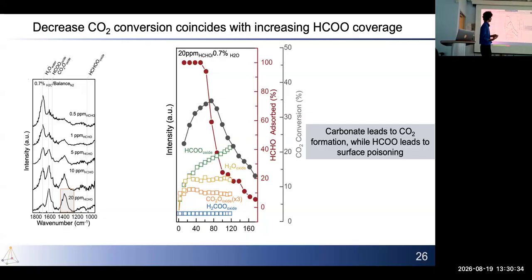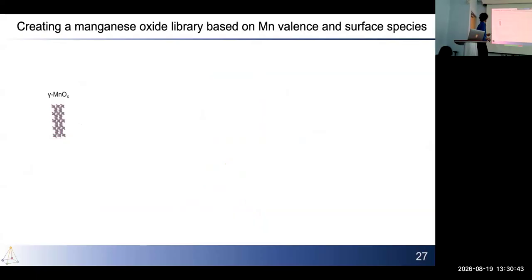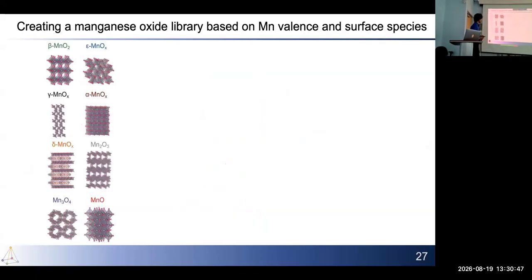We had a reaction mechanism based on spectroscopy, but could we extend this hypothesis to other manganese oxides? The manganese oxide I spoke about so far was the gamma manganese oxide. So we created a whole library of manganese oxides, looking at about 8 different ones to see if the hypotheses and trends we saw with one particular manganese oxide could be extended as a design principle.